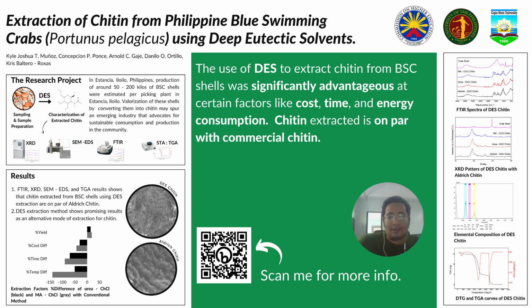First, you can scan the QR code on the poster for a more detailed presentation of the study. The main highlight of the study shows that deep eutectic solvents can extract chitin from blue swimming crab shells. Specifically, we used malonic acid choline chloride and urea choline chloride for the deep eutectic solvents.